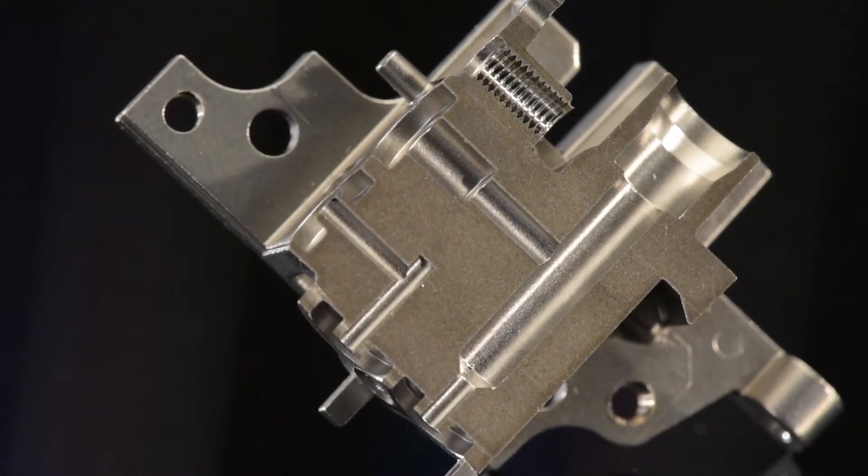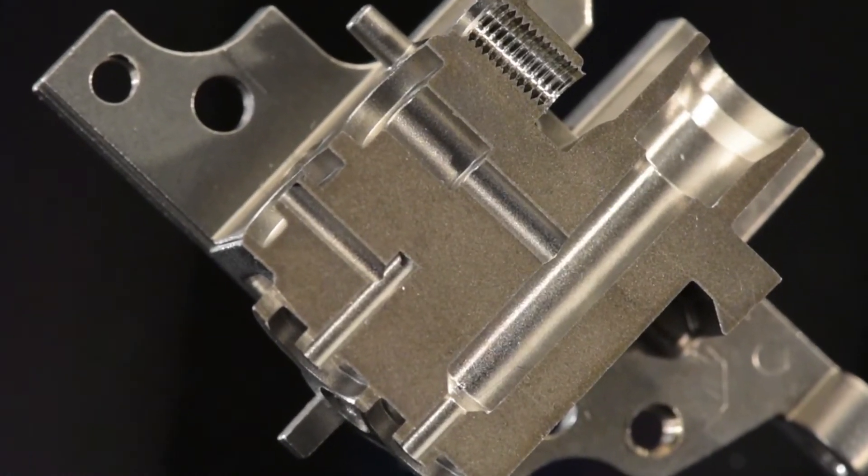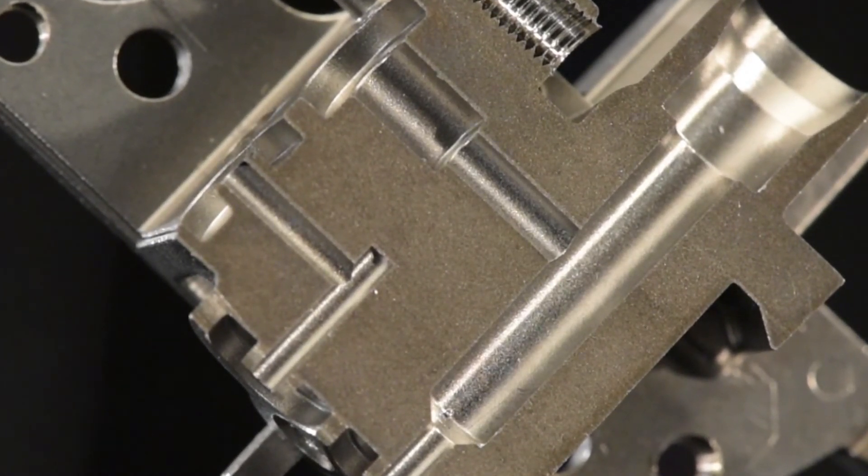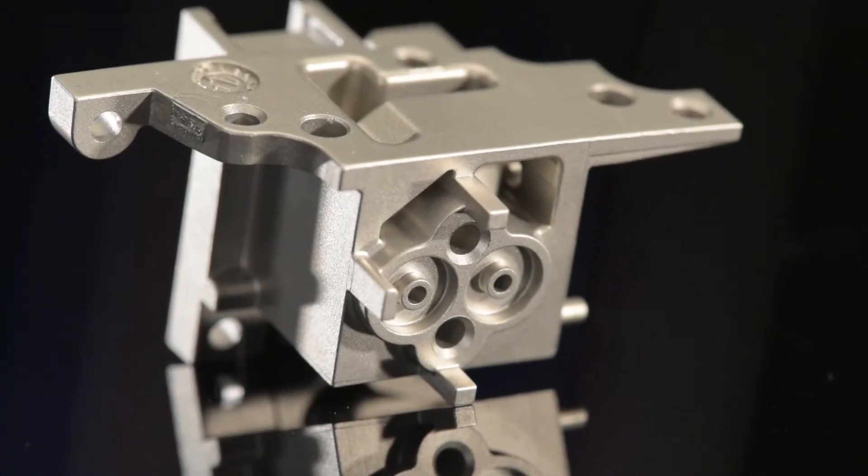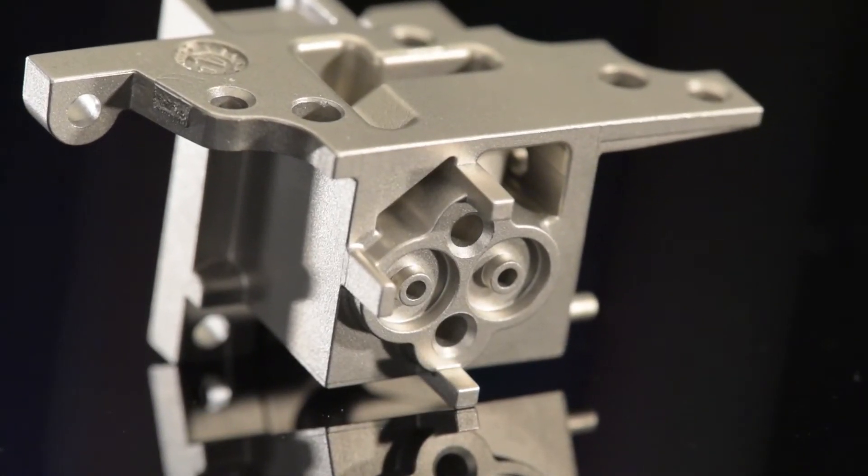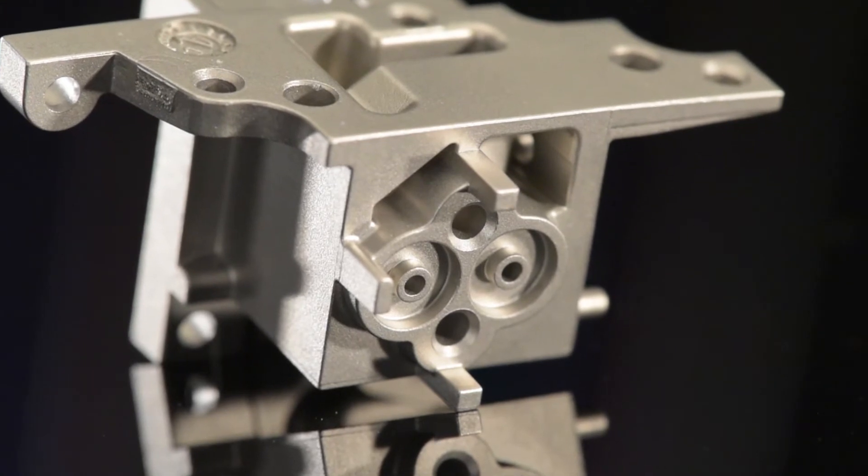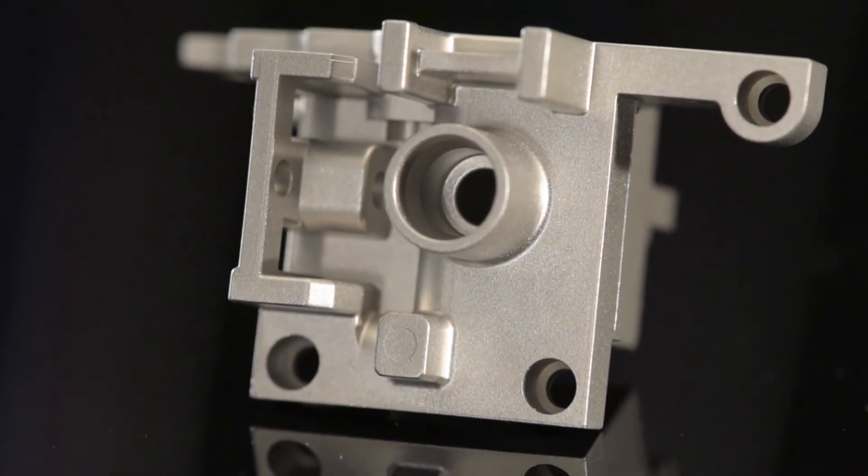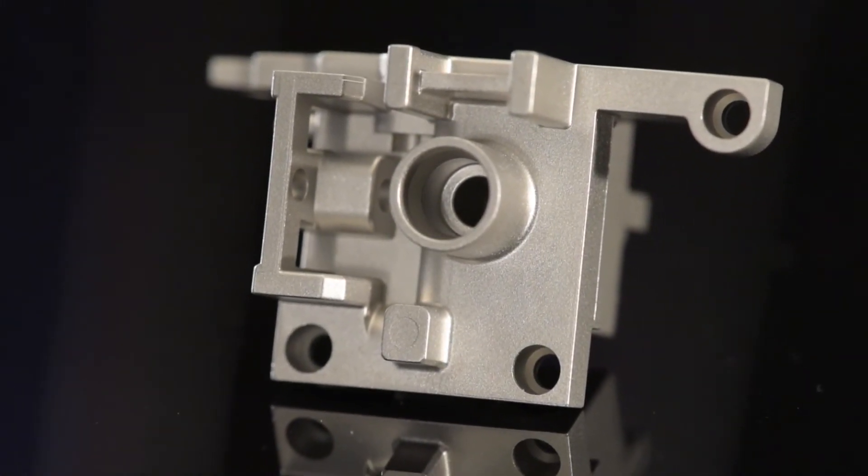Forming these 90-degree three internal channels without flashing required the use of a hydraulic core pull slider system to ensure smooth operation. By integrating multiple formerly cast and machined parts into one MIM component with several through holes, intricate features, and walls less than 1mm thin, its complex geometry became quite challenging for tool design as well as for the MIM process.